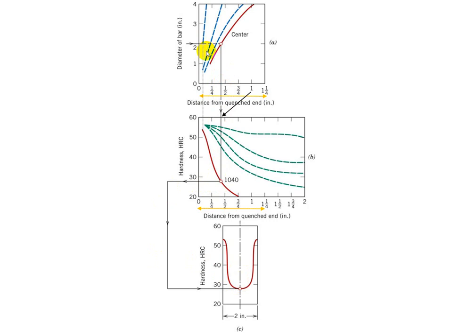So the next one is you want to do this for example at the surface. You go from here and here, and then this goes here. Surface, center, two more points required. I go here, three-quarter, find the hardness from here, I go, I put it here. One more point. And then I do for half of the radius. Obviously in industry you can have more than four points. You can have 10 points every 10 percent. And in this case you will have 10 points here, or nine points here, nine points here, and one point here. So you will get a more coherent and consistent graph.